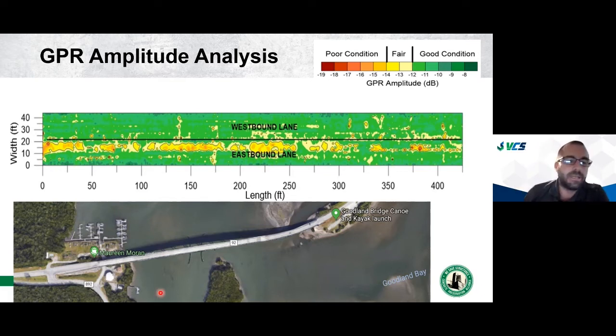And so what you're getting is salt water exposure on the right eastbound lane of that bridge for the first half. And so you can see here's a GPR scan of that bridge deck. And we see a lot of attenuation, the yellow color, in the eastbound lane down the center. And that's exactly from salt water coming off those boats. And so, looking at this scan, I can't tell you, oh, this area is delaminated and this area isn't. I can't discern what is damage and what isn't in this image. But what I can tell you is, okay, the eastbound center lane has a condition that either is damage or will lead to deterioration in the future.